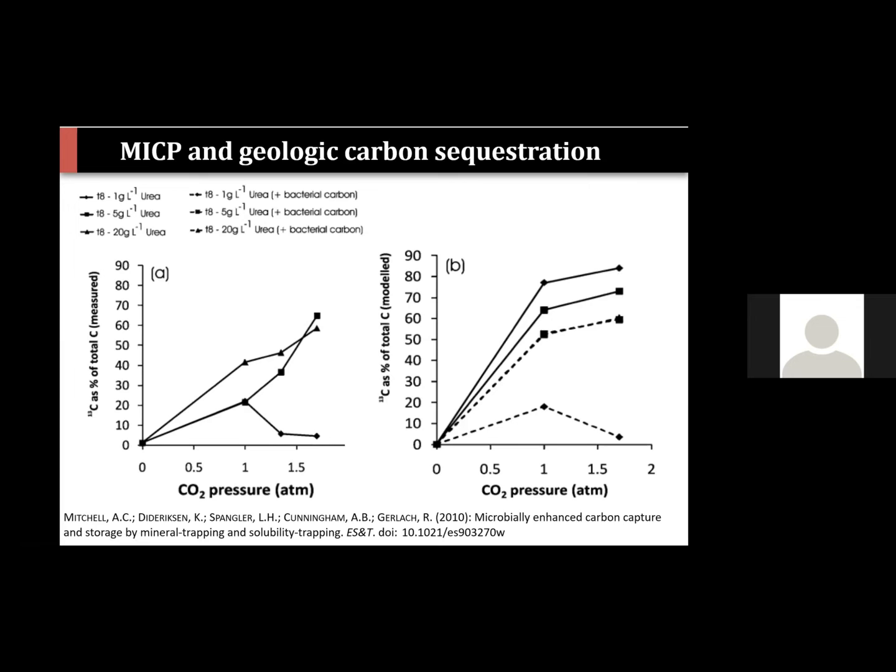Now, while we're obviously forming calcium carbonate and we're showing that there is diffusion from the gas phase into the carbonate mineral, ultimately, of course, the moles of calcite precipitated are broadly equal to the moles of carbon derived from the urea itself. So obviously you don't get any net precipitation of CO2 in the calcium carbonate. So, in a sense, for mineral trapping, this particular mechanism doesn't hold any great weight.